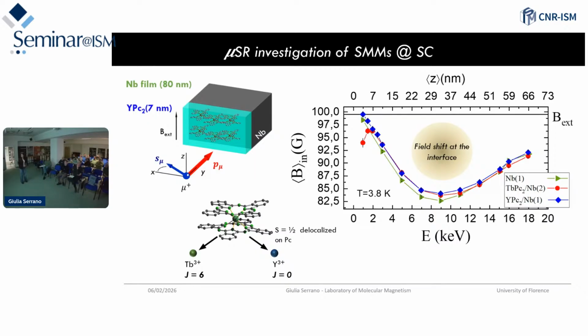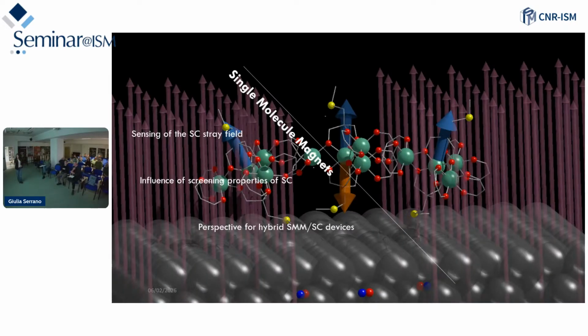What we observe here is that, as you can see, at the interface we don't have any strong shift of the internal field, but we have a case in which we somehow replicate the behavior we observe on the bare niobium. So we have to understand the reason why terbium Pc2, the magnetic moment, is doing that to the superconductor. The idea now is that the dipolar field exerted by the terbium Pc2 molecule can be directed in the opposite way with respect to the external field, and then can screen out the field and help in this screening. But these are, of course, data and investigation that we need to rationalize further.